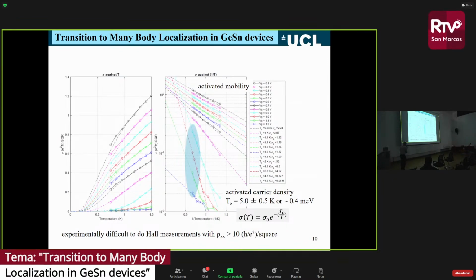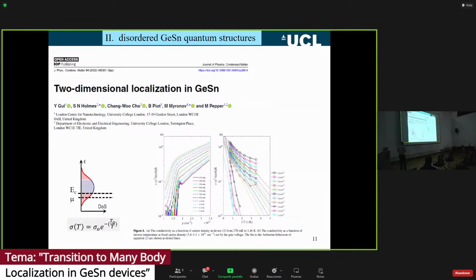We're still in this thermally activated conductivity region. Just to put some of the numbers in, this activation, this characteristic temperature T0 is about 5 Kelvin. So that's the thermal energy between the mobility edge and the chemical potential, which is about 0.4 meV. Okay, so it's all low temperatures. To see an activated conductivity here, we'd have to be significantly below 5 Kelvin. Okay. We published some of this data last year. That's the same set of data.